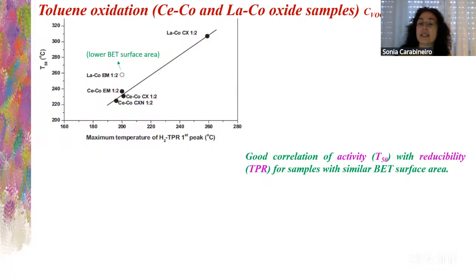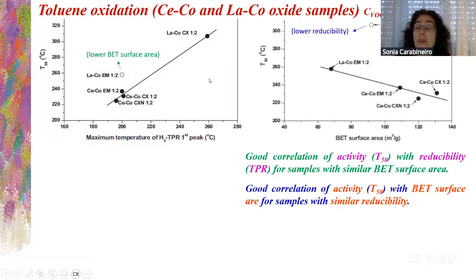But for samples with a similar BET surface area, because this one in white had a lower BET surface area. So this one was like that. Also, we obtained a good correlation of the activity with the BET surface area, but for samples with similar reducibility, because this one, the La-Co EM 1:2, is a bit far apart from the correlation, but it had a lower reducibility. So you see that both things are related.